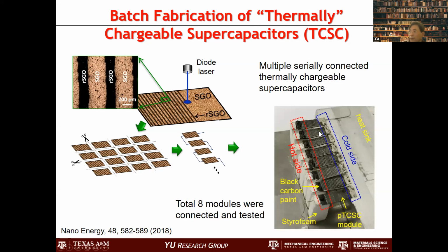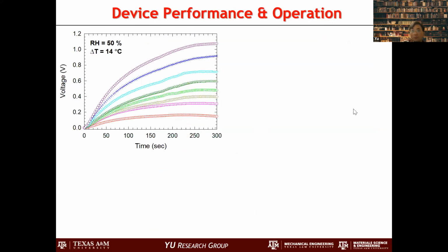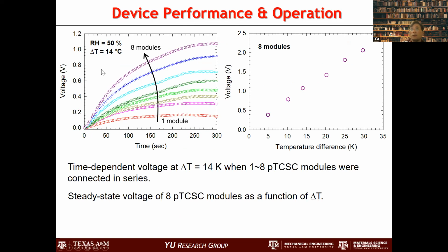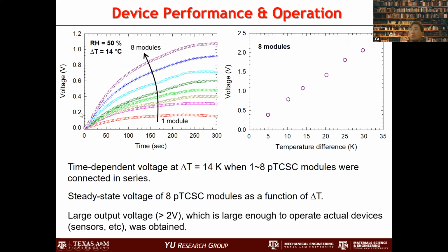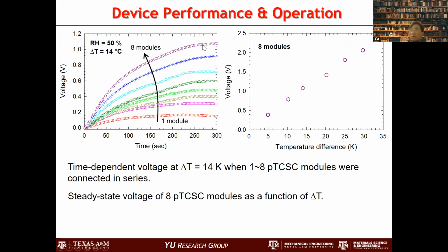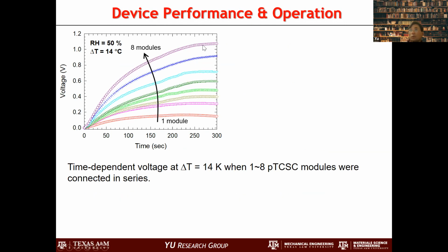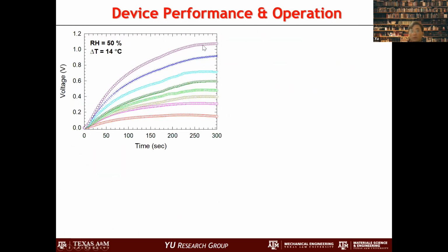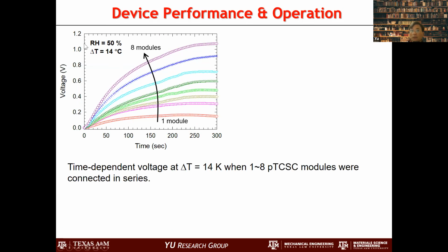So we made 8 devices connected in series, and make one side hot, the other side cold. And then we can raise the voltage a lot. So we have a total of 8 modules. And as we connect more and more devices, the voltage here is raised up to 1 volt, as you can see, and it's pretty large here, and okay, my computer is lagging. And this is only at a temperature difference of 14, which is not that high. So which is really good.